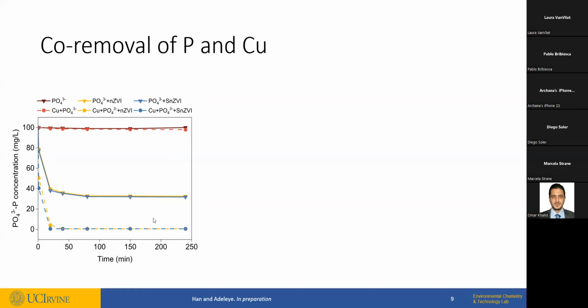Now here's where it gets interesting. When we now add copper to the phosphates with the NZVI and SNZVI, we see complete removal of both contaminants within about 40 minutes, and by 4 hours at the end of the experiment, they are both gone. So this was an interesting result because unlike GAC, where an additional contaminant decreases overall performance, what we're seeing here is that an additional contaminant improves the overall performance.